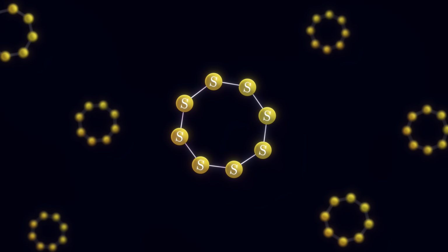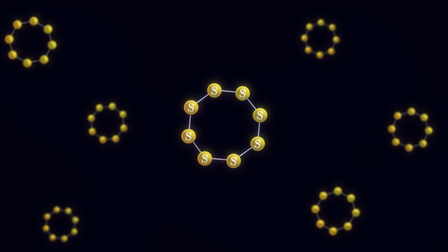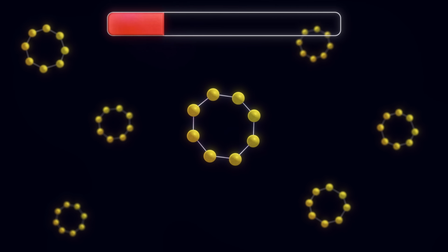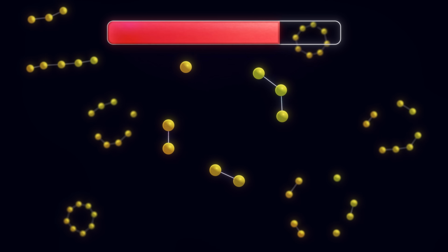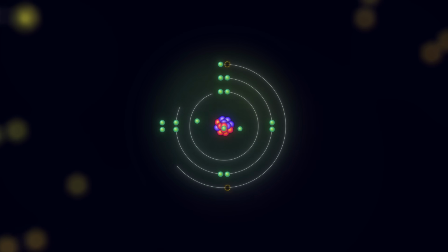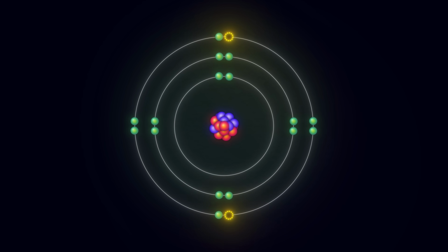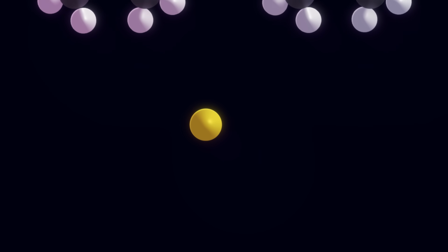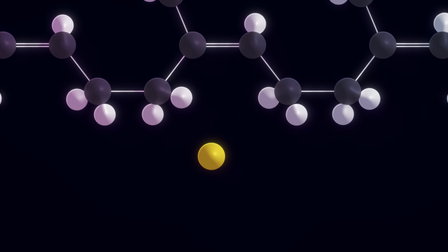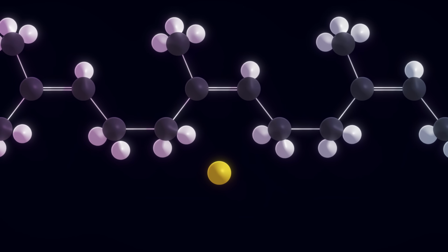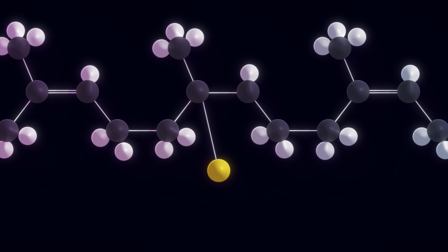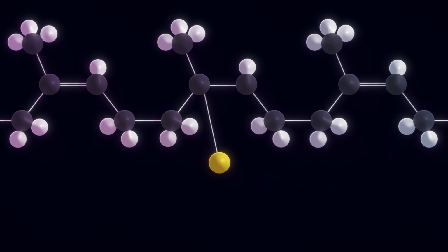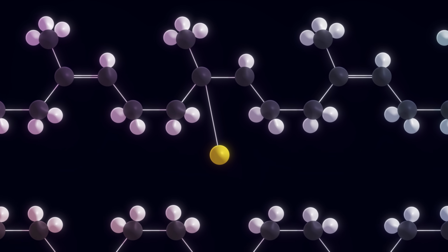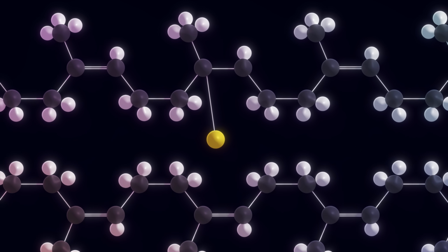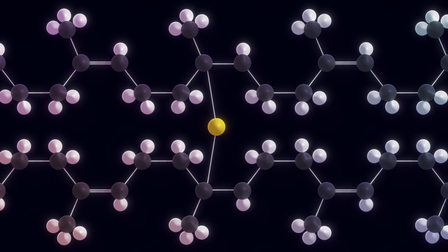Well, chemically, sulfur powder is just rings of 8 sulfur atoms. On the hot stove, the sulfur ring broke apart into smaller pieces. And now those sulfur atoms, or sulfur chains, have free bonding sites, so they look for places to attach. What likely happened is they grabbed onto a carbon atom from a rubber chain, breaking its double bond and attaching itself. Then with another free bonding site, it grabbed onto a carbon atom from a different rubber chain, breaking its double bond and linking the 2 rubber chains together.